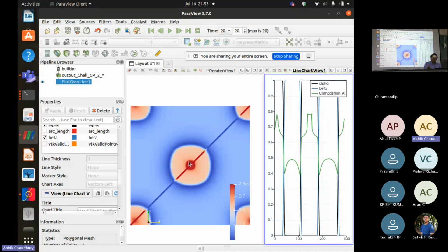No, the red one is the starting solid composition that you started with. That is slightly off because you're starting with the equilibrium composition, and then you are at the undercooled temperature, so it will take a new composition with which it will grow. So it's different from this, but there is no homogenization happening between the two because there was no solid diffusivity. It will take, in this particular case, infinite time, because solid diffusivity is 0. If you use a finite diffusivity of the solid, you will see a finite time in which this will diffuse.